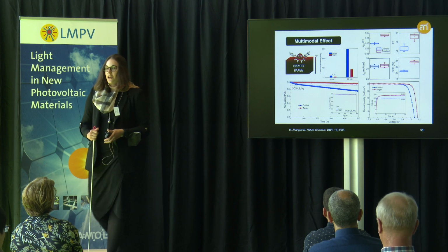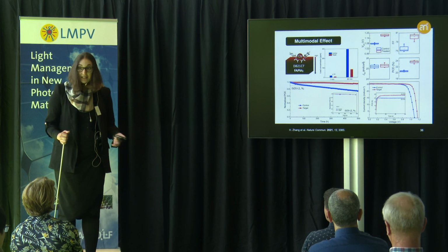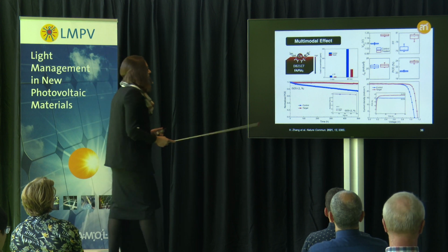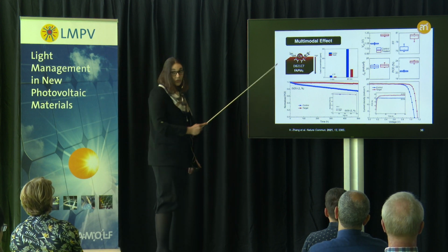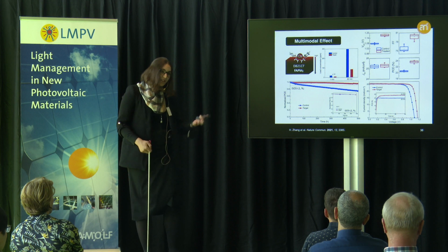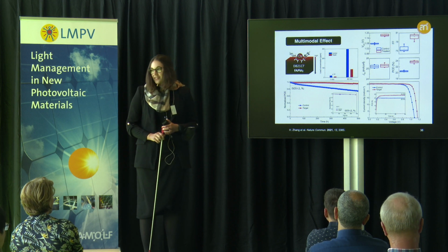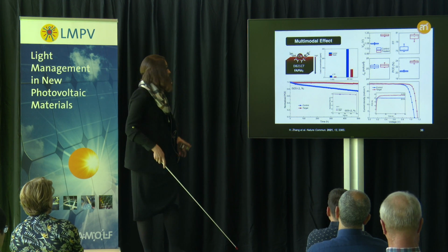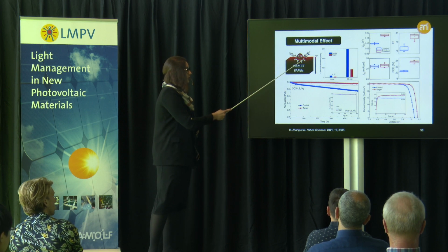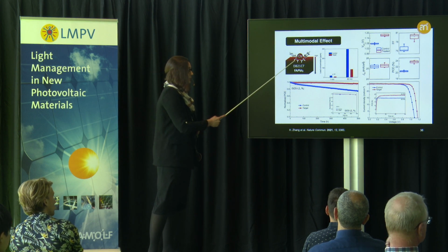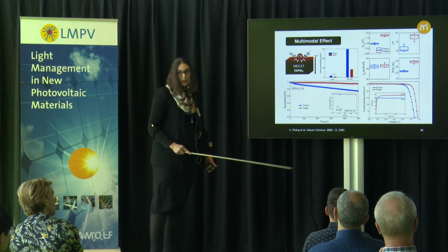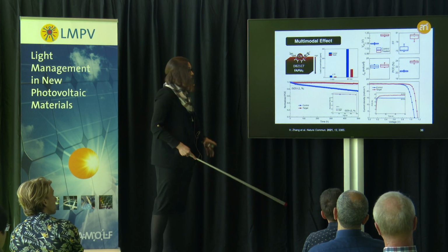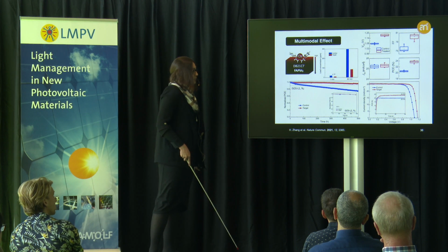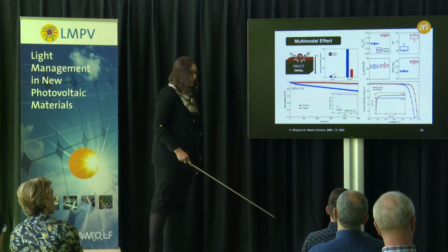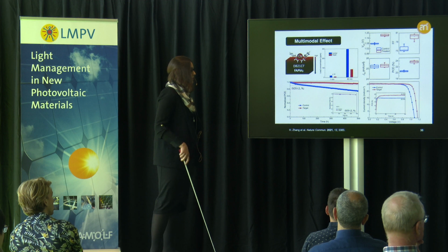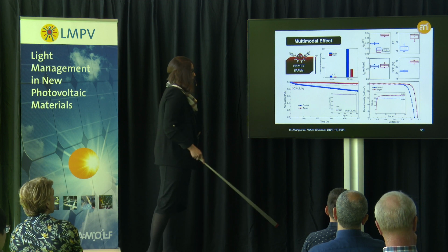for the purpose of photovoltaics, but which is notoriously unstable, as its perovskite form cannot even thermodynamically be accessed at ambient conditions, which can be to an extent circumvented by using smaller cesium cations, yet at the expense of its optoelectronic characteristics, which is something that we circumvent by relying on this gradient of cesium cations to really stabilize the resulting material without compromising the beneficial optoelectronic characteristics, further enabling competitive performances and maintaining these large beneficial operational stabilities even at elevated temperatures.